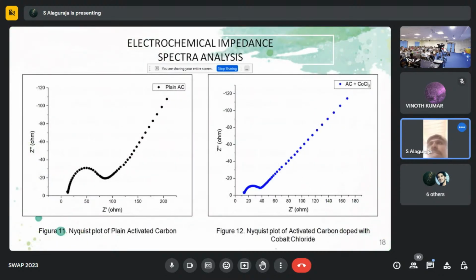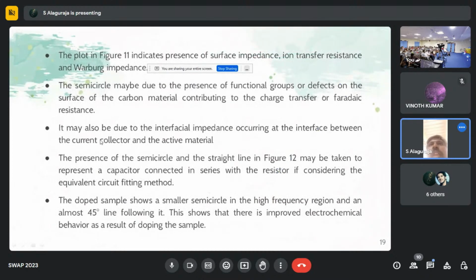Electrochemical impedance spectral analysis. It may be due to the interfacial impedance occurring at the interface between the current collector and the active materials. The presence of the semicircle and the straight line may be taken to represent a capacitor connected in series with resistors in the equivalent circuit. The doped samples show a smaller semicircle in the high frequency region and an almost 45-degree line following it.